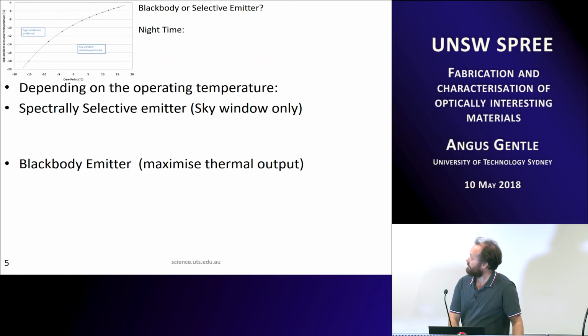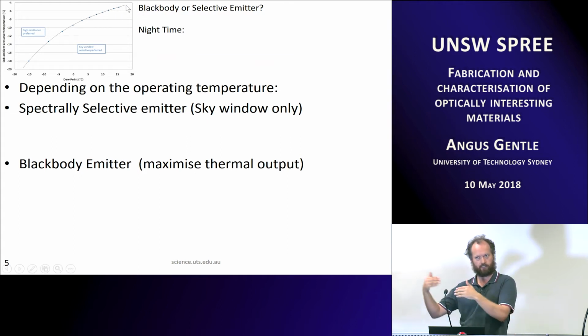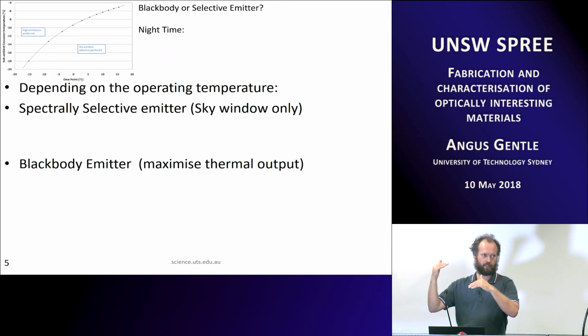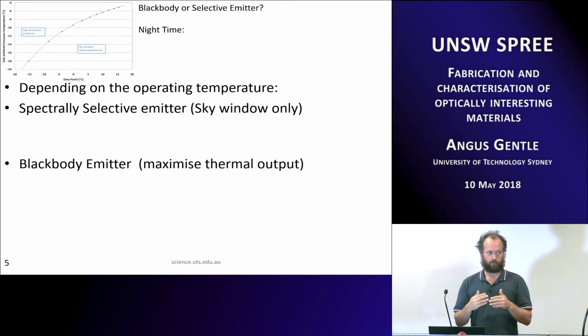So, as I was saying before, it sort of depends what temperature you're at. And this is one that we're still trying to get across to some groups that work in radiative cooling, is when you're better off having a selective emitter. So you've actually got to look at the radiative flows at all the different wavelengths and then work out the total power and see that you're actually better off in most real world cases. So if you're doing it on roofs or solar panels, if you're above ambient temperature, you're better off with a black body. There's no question about that at all. But once you start to drop below about 4 or 5 degrees below ambient, a selective emitter may be better, but you have to be able to get into that regime.